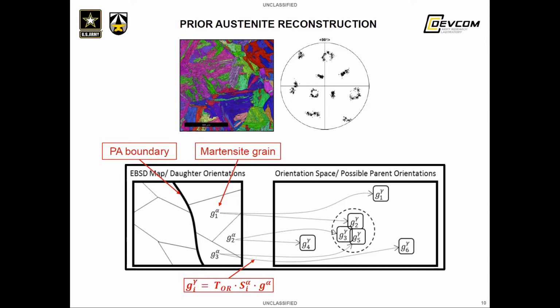All of the possible parents for the neighboring martensite grains have been generated using the inverse of the orientation relationship. Some of these parents are very close to each other, which you'll notice. The dotted line there indicates some notion of tolerance. If a group of possible parent orientations are within some misorientation tolerance of each other, then those three martensite grains you would say could be grouped together, and the parent austenite orientation that you would assign to that group of martensite grains would be the average of these overlapping orientations in orientation space. And so essentially you would compare neighbors to neighbors.